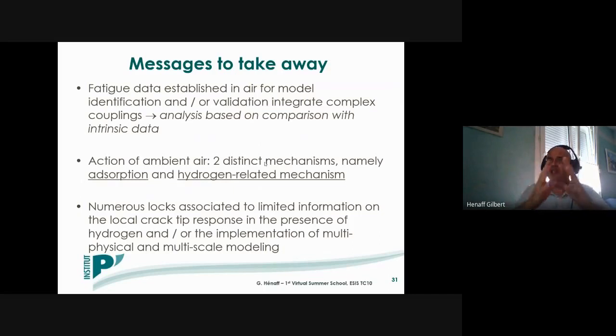And the second point is that I hope that I've convinced you that the action of ambient air in the near threshold region is due to the combination of two distinct sequential mechanisms, namely water vapor adsorption and then hydrogen-related mechanisms. But the point is that today we still have numerous gaps associated to the limited information on the local crack tip response to the presence of this moisture or dissolved hydrogen, in order to have a complete description of the process at the crack tip.